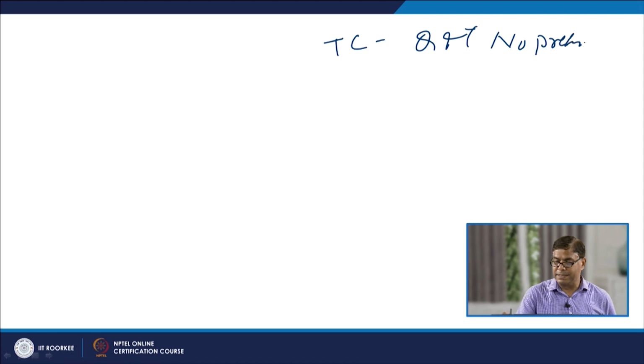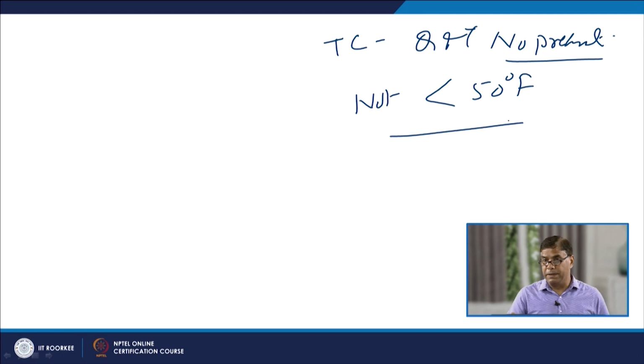Normally, as I said, in case of thermal cutting of these Q&T steels, no preheat is needed, provided the plate temperature is not less than 50° Fahrenheit. If the plate temperature is less than 50° Fahrenheit, then we must preheat at least up to this temperature.